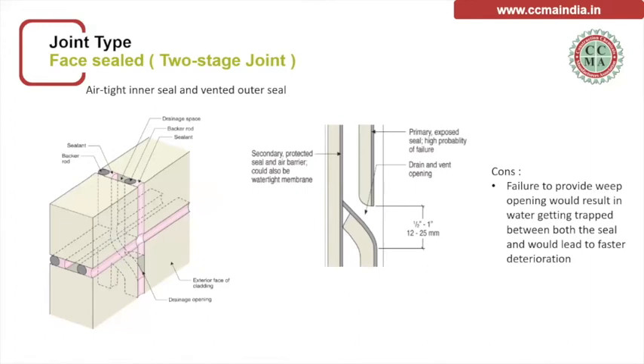Second type would be the face sealed two-stage joint. Here you have an extra line of defense. You are building a redundancy in the system by providing a seal from the inside as well. So on the outer side you have a primary sealant which is exposed, and this would deteriorate faster than the inner sealant. The secondary sealant provides the air barrier, so it is not exposed to UV light.